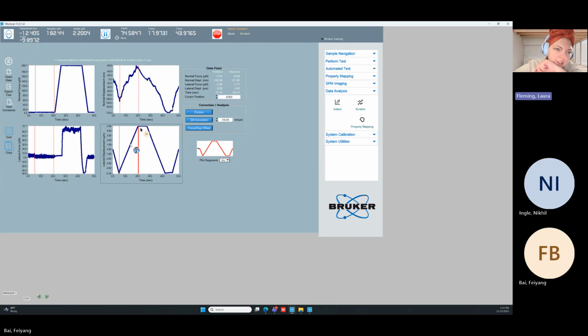So yeah, the reason I had this one moved in a little bit is, do you see how there's like this bump and then it goes down? I think that that's artificial and I want a better measurement. So I think that this is a more accurate representation of the sample tilt than going to the other side of this bump. So that's why I'm headed there. But yes, now you can hit tilt correction and it's going to make these 2 at the same lateral normal displacement or very close to it.